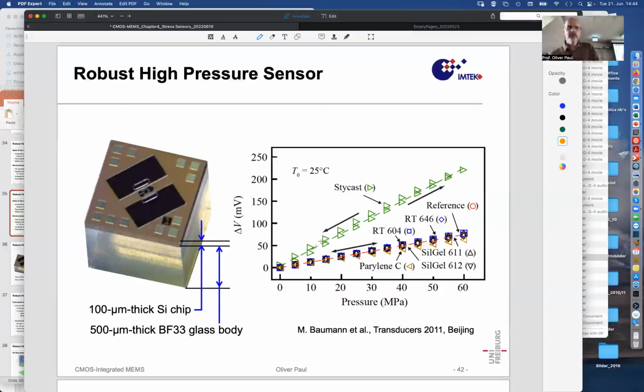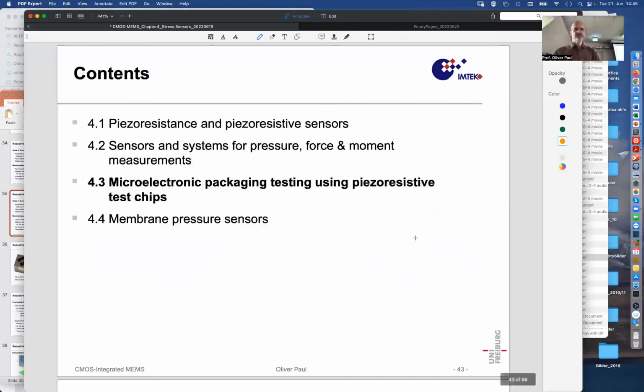And so, well, at least for the StyCast, he could see that, okay, there is a big hysteresis. So going up in pressure and down in pressure is not the same thing. So that's not a good example. And then for the other materials, it was kind of okay. But of course, I mean, that was just an initial study. That's not a product development. And so likely for a product development, many more such measurements under much more severe conditions, with more cycles and temperature variation and optimization of the curing conditions of the materials, processing conditions, in particular curing conditions of the materials in situ would be necessary.